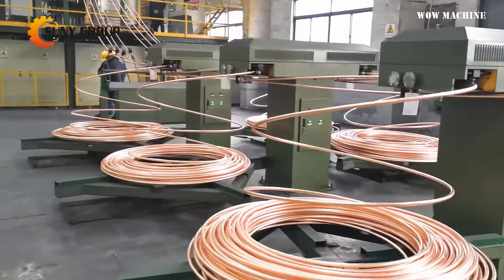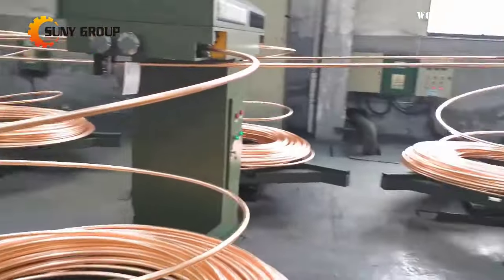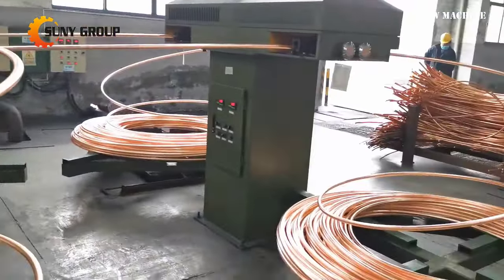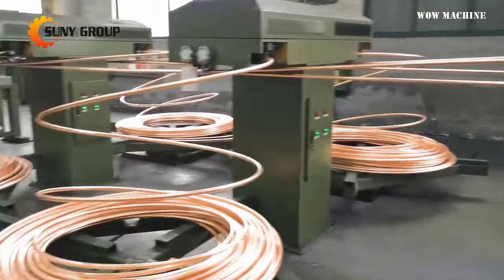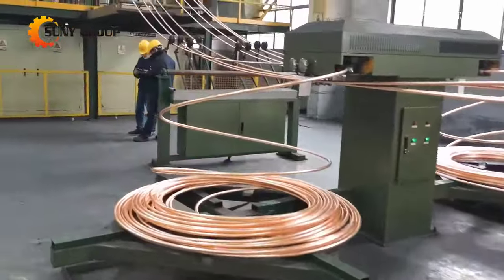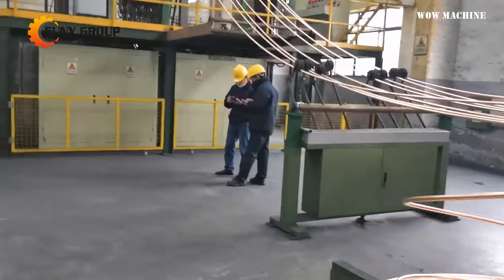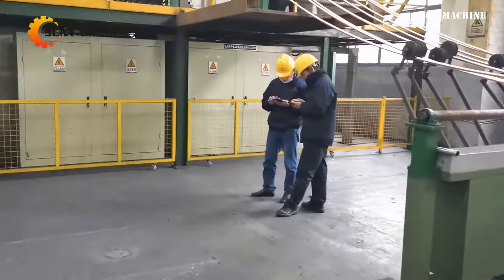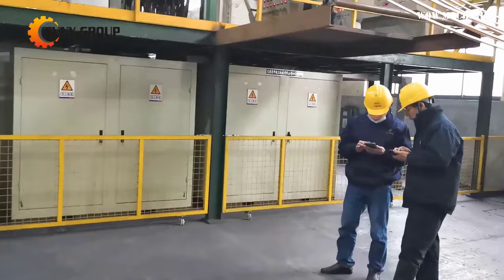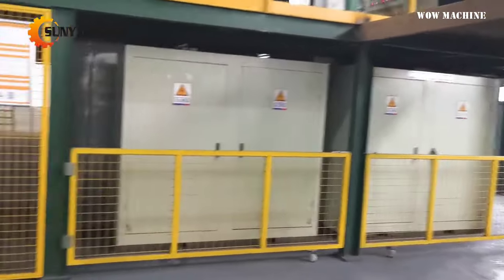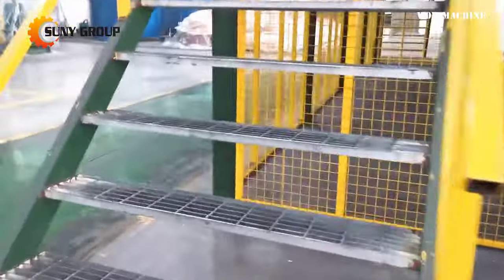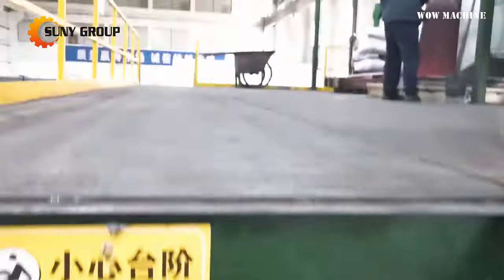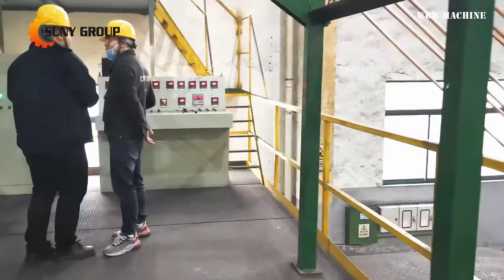The continuous casting process allows the molten copper to form a long, continuous billet or bar as it exits the mold. This process is crucial because it ensures that the copper maintains a uniform structure, free from internal defects. The casting process is closely monitored to maintain optimal temperatures and solidification rates, ensuring the copper has the desired properties for subsequent processing.